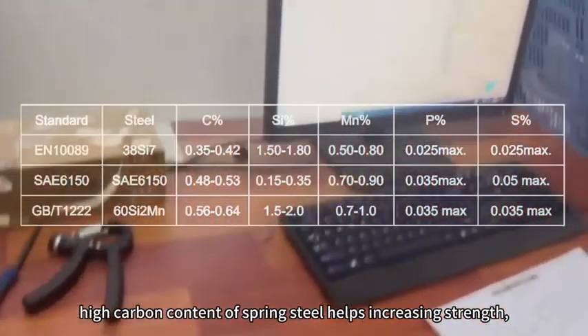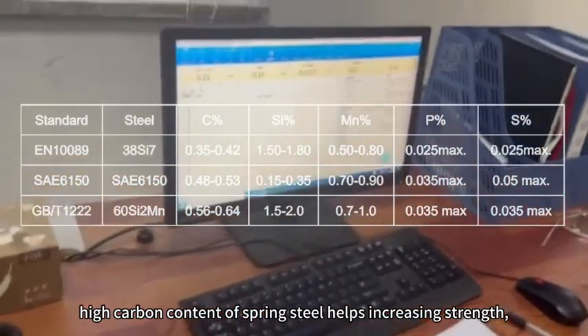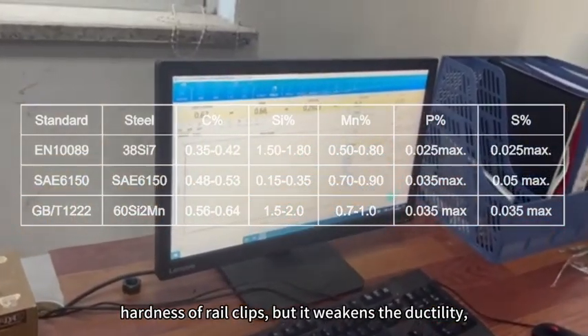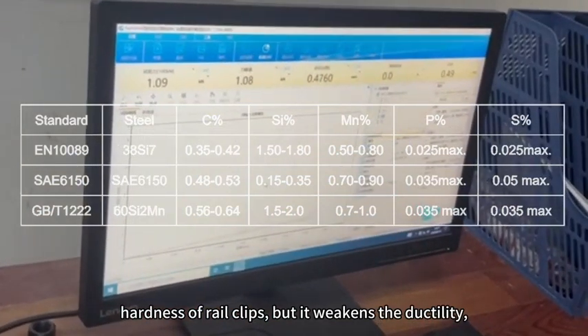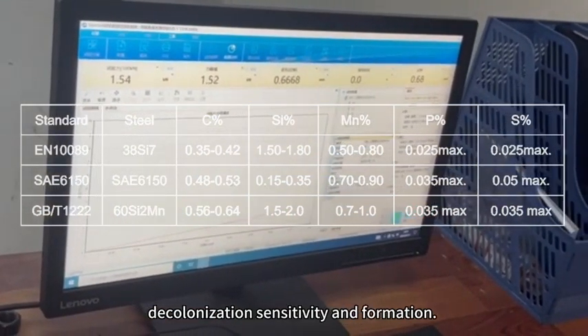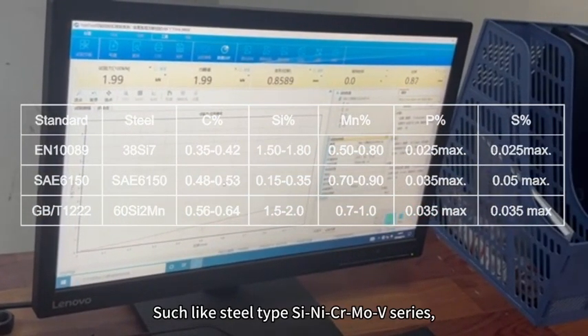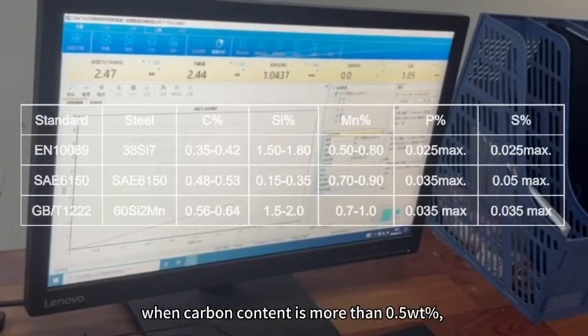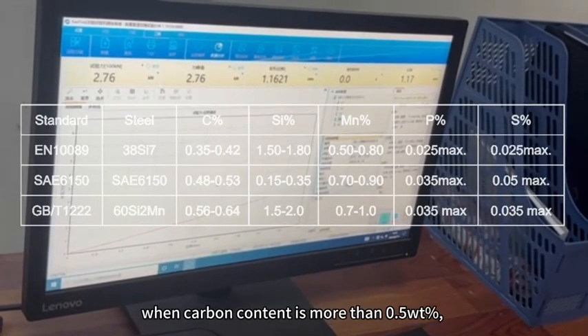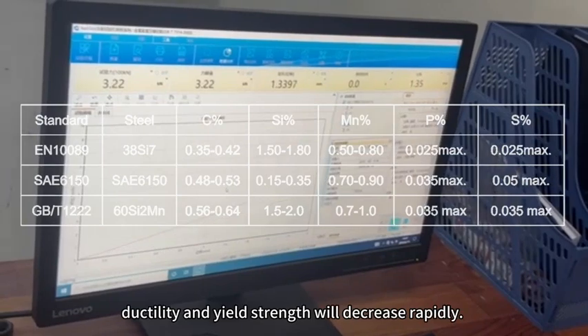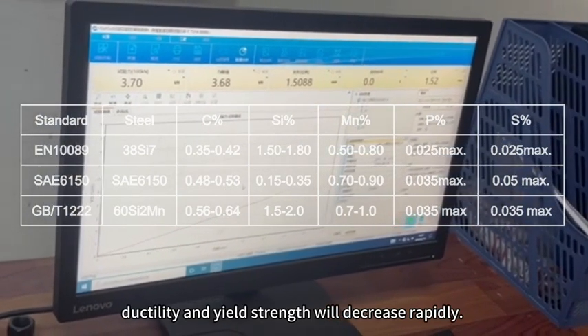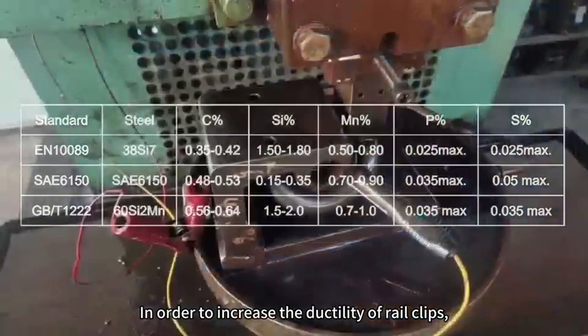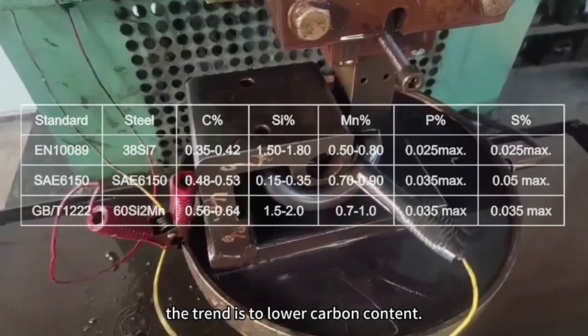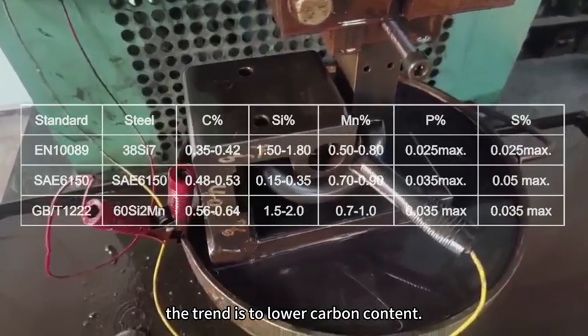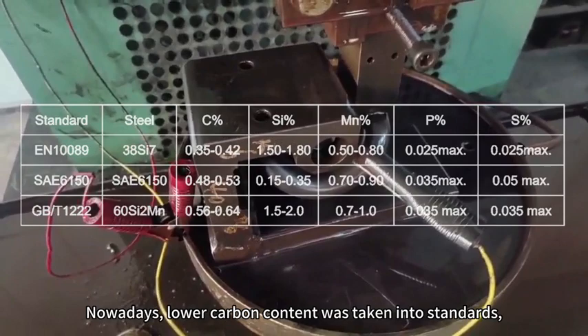However, there is recent analysis saying that high carbon content in spring steel helps increase the strength and hardness of rail clips, but it weakens the ductility, decarburization sensitivity and formability. For steel types such as the Si-Ni-Cr-Mo-V series, when carbon content is more than 0.5 Wt%, ductility and yield strength decrease rapidly. In order to increase the ductility of rail clips, the trend is to lower carbon content. Nowadays, lower carbon content has been taken into standards.